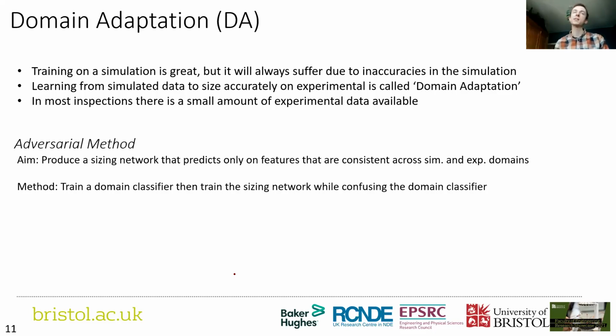What it says is that the best sizing network would be one that predicts only on features that are consistent across your simulation and your experimental data. So to do this, you train a classifier that, given some data, tells you whether it's simulated or experimental. It gets really good at doing that. And then when you train your sizing network, you maximally confuse it.